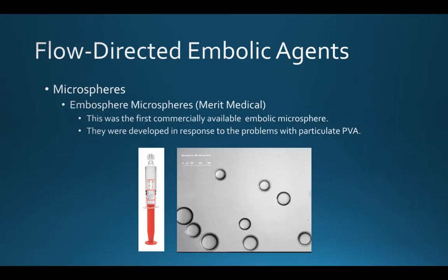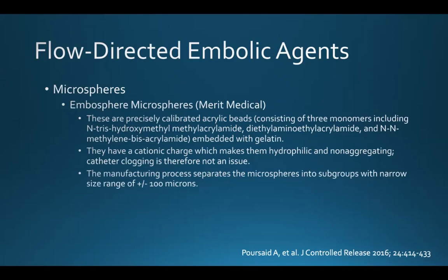Embosphere microspheres were the first commercially available embolic microspheres, developed in direct response to the problems with particulate PVA. Embospheres are precisely calibrated acrylic beads embedded with porcine gelatin. They have a cationic charge, which makes them hydrophilic and non-aggregating, so catheter clogging is not an issue. The manufacturing process separates the microspheres into subgroups with a much narrower size range than particulate PVA — in the case of embospheres, that size range is usually plus or minus 100 microns.